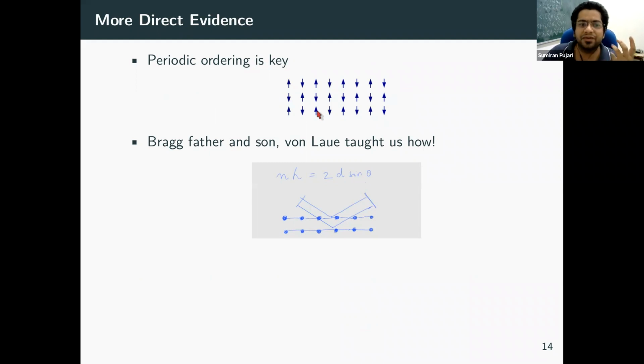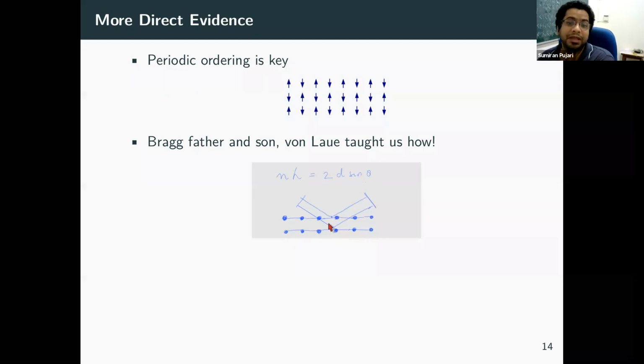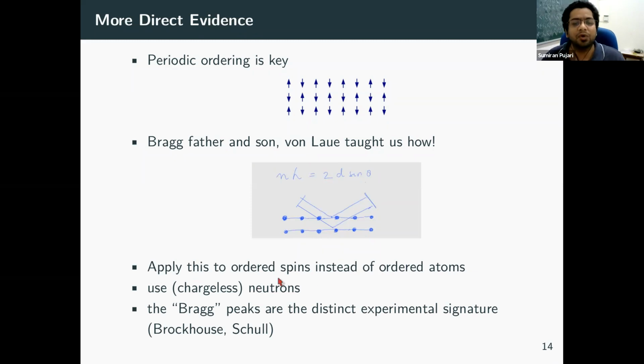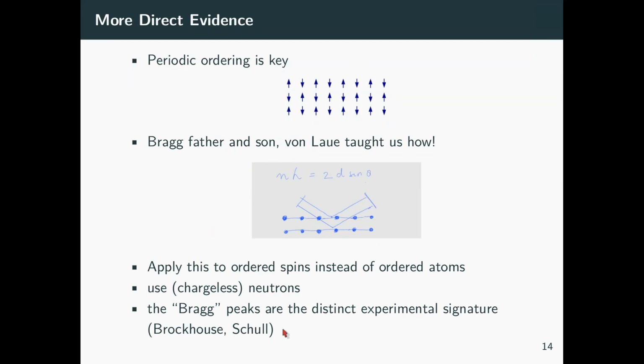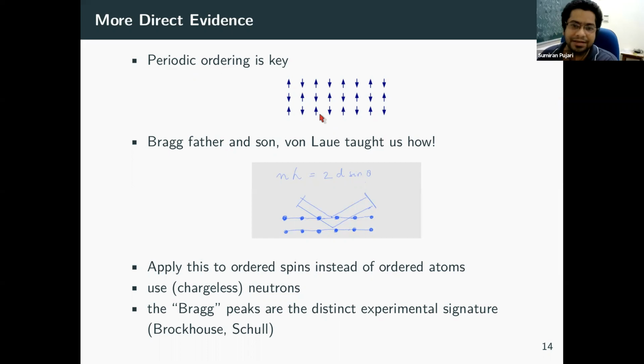We know how to check for this, and we have learned it in a different context in terms of X-ray diffraction. If we have a periodic arrangement of crystals, we can do X-ray diffraction and see Bragg peaks due to the periodic arrangement of the atoms. You use that same idea, but now for ordered spins, and for that it turns out you use neutrons. I can't go into the details of this neutron diffraction measurement, but you can see Bragg peaks if you shoot neutrons on such a periodic arrangement of spins, up, down, up, down. And if there is a Bragg peak corresponding to this ordering, that would be direct evidence of spin ordering. This was done eventually for the Néel state, and thereby it was recognized that Néel's antiferromagnetic state is a bona fide state of magnetic matter.